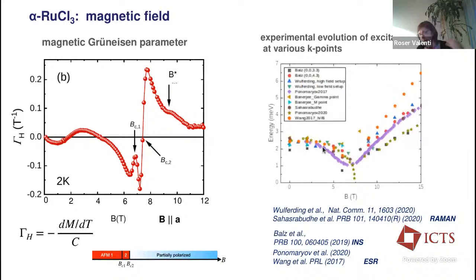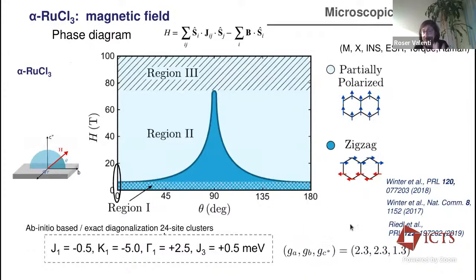And you see that basically this is the lowest excitation energy reported, here in the zigzag phase. So the excitation energies come into values between 6 and 9. And then the next excitation would correspond continuously to this partially polarized or fully polarized phase, if you go to infinite magnetic fields. So it's very hard to say here that you are having a distinct intermediate phase, because if it's a spin-liquid phase, this is a topologically non-trivial phase. Your ordered phases are topologically trivial, so you should have, thermodynamically, in fact, a phase transition showing. So you see the dispute about the origin, whether you have this intermediate phase or not.